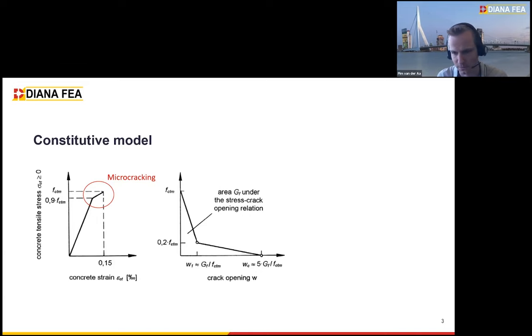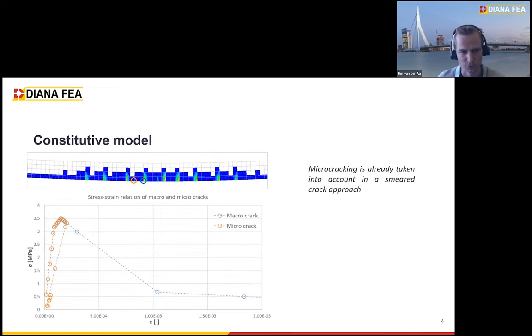But what does this mean for nonlinear finite element analysis? In most cases, you model it with some sort of smeared crack approach. And in general, if you already model it with a smeared crack approach, the micro cracking is already taken into account. So when we look at nonlinear finite element analysis, I don't think there's any need for this branch. And I have an example to show you this.